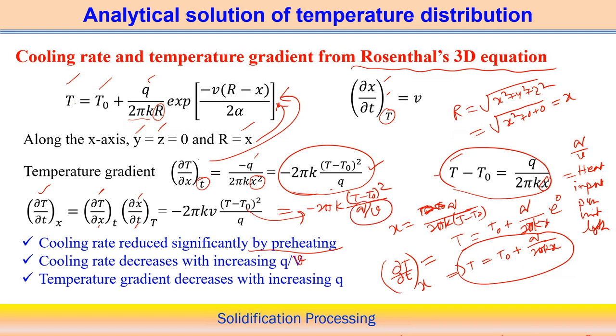Cooling rate also decreases with increasing Q by V, that means heat input per unit length. By increasing this value, Q by V, the cooling rate actually decreases. Increasing Q by V can be done in two different ways: either we increase the heat input to the welding process, or the velocity is low. In these two cases, Q by V can be increased, and by increasing this value, the cooling rate decreases.